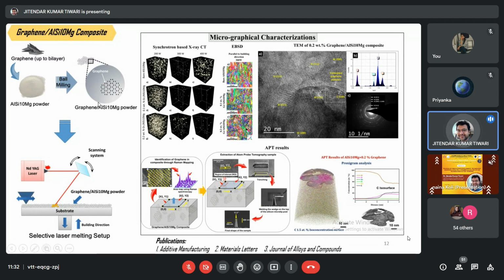How we developed this material, I'll just quickly explain: we mix graphene with aluminum, and then we do ball milling, and then we load it into the laser powder bed fusion system, as I already explained about the laser powder bed fusion technology. In this way we can do some kind of printing, and then we find this kind of solidification behavior.